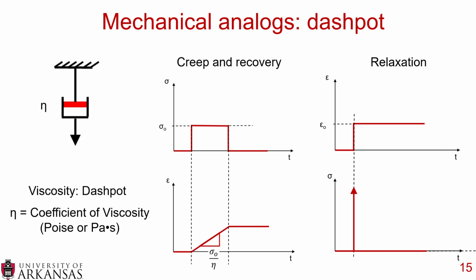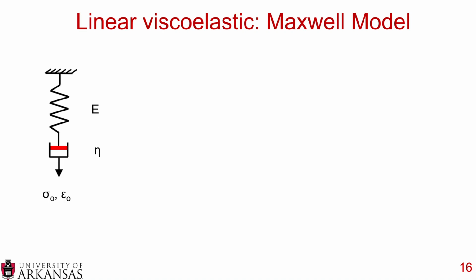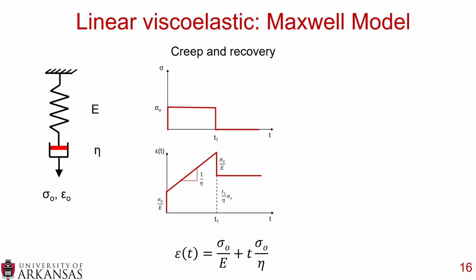Now it's not very convenient to have just a single spring or dashpot, so we also put these together. So for linear viscoelastic behavior, we have what's called the Maxwell model. And this is where you have one spring and one dashpot in series. And you either apply some sort of stress or some sort of strain. So when we're looking at the creep and recovery, you apply some sort of stress, and then at T1, you remove that stress. And you can see here, the second you apply that stress, a deformation occurs, and that is the stress divided by the modulus of elasticity.